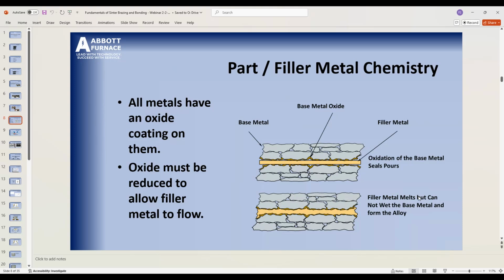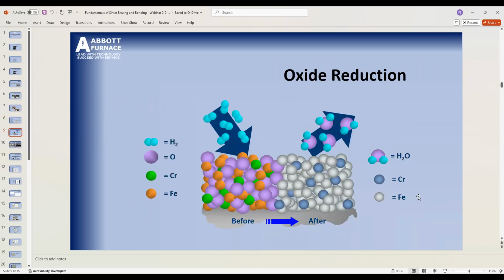And if we have any metal, it will oxidize, or most metals, I should say, will oxidize, and you have that thin layer on it. And so we have to remove that oxide layer to allow that filler metal to touch the components and actually form the bond. And so the way that we get rid of that oxide is we typically use a gas that contains hydrogen, okay? And the hydrogen comes in, and we want the hydrogen to want the oxygen more than what the metal does, okay?